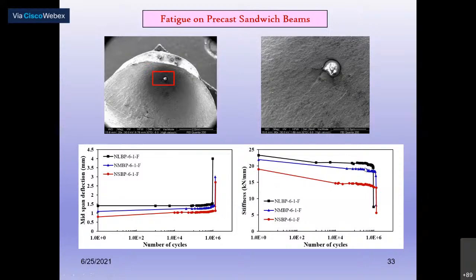With subsequent loading and unloading, more microcracks joined together to form macro cracking. So the stiffness decrement is never gradual; it looks intact, but suddenly, when something is happening inside, it is a progressive failure, and one day you find complete collapse of the structure. That is the thing in fatigue loading: in all structural systems, we have to ensure a minimum life. The deflection was almost constant, but we never expected this to happen at the end. The life was okay, but it failed earlier due to the defects.